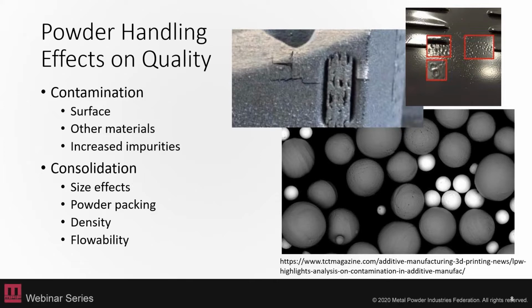On the right here, there's an example where an aluminum build was affected by contamination from a nickel-based superalloy powder. And this happened just because a new employee wasn't properly trained and aware of the issues with powder handling, and they were unable to get good builds in this plant because there were nickel-based superalloy powders that were coalescing within the build and causing these crack features. And so that's just one example that it was just an awareness issue and a new employee that wasn't fully trained. And once they were able to diagnose that and analyze the problem and really be aware upfront of the issues with powder handling, as a challenge for any company, it's really something that you need to be careful about as part of the project workflows.